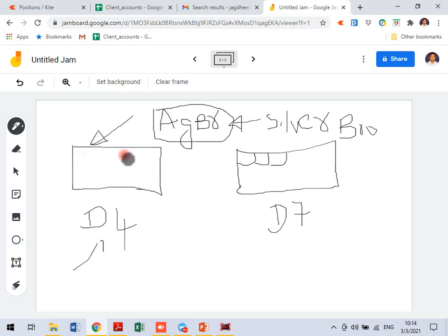Like this. Okay. So what happens when radiation comes here and hits it? How much area is it exposing? This much area is already exposed with one ray. But here, with one ray, only this much area is exposed. Correct? So the area of exposure in D4 is very, very low because the silver bromide crystal is small. So obviously you need more time.